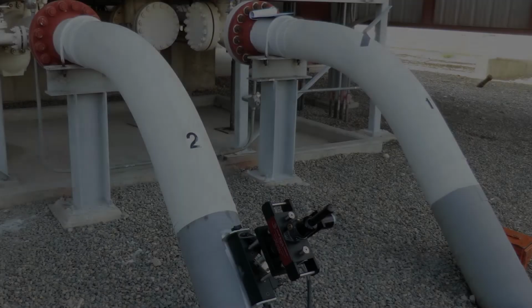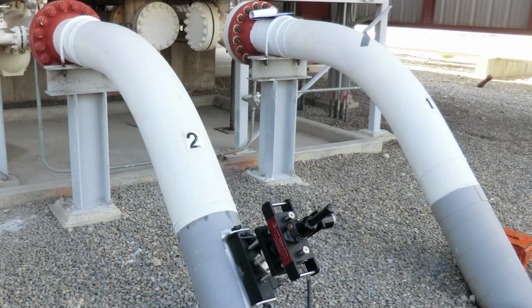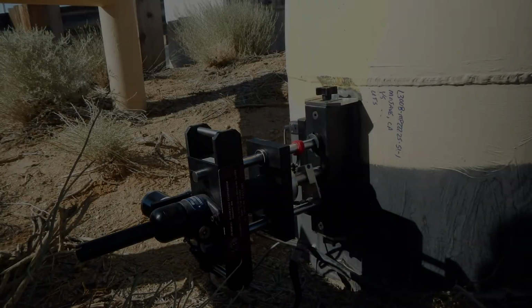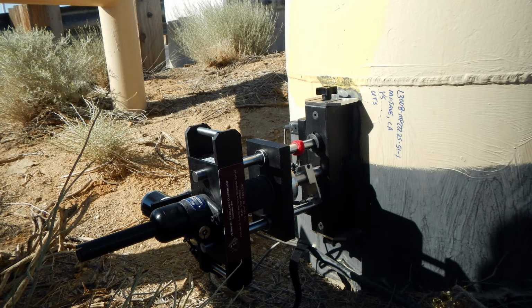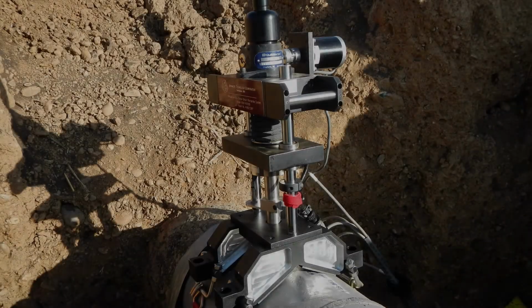The ABI test results are within 5% of the results from destructive tensile specimens and within 10% of the destructive fracture toughness tests. The ABI test was invented 25 years ago as a field test and to replace the destructive tensile and fracture toughness test. It is very well suited for the petroleum industry, where an oil or gas pipeline can be tested in service and under pressure.